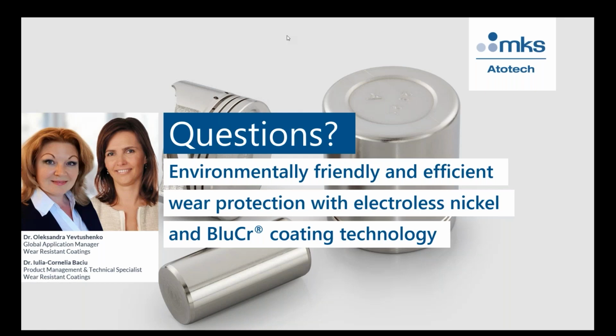What is the variation in thickness with EN process when plating rack versus barrel? Yes, I can answer this question since it's a matter of electroless nickel. So with electroless nickel, as I explained, we don't need any current. Ideally, we don't have any thickness variation between rack and barrel. Any variation which can be observed is due to other factors like solution dynamics or some temperature variations, pH variations, lack of agitation in the bath after replenishment, and things like this.